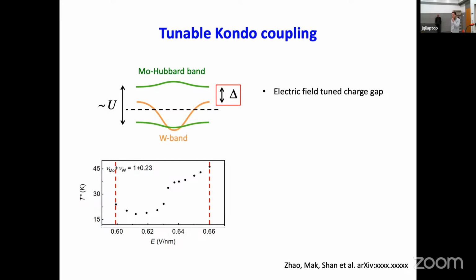So those are two different samples, and typically it's way harder to make these electrical transport samples. If they are as disordered as what I showed you for the optical sample, then you cannot really measure anything too meaningful in a transport device, because we measure globally throughout the entire sample. So those are totally different samples, and typically we shoot for really homogeneous samples for the transport measurement.